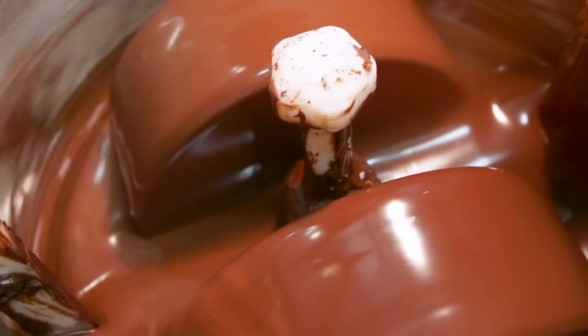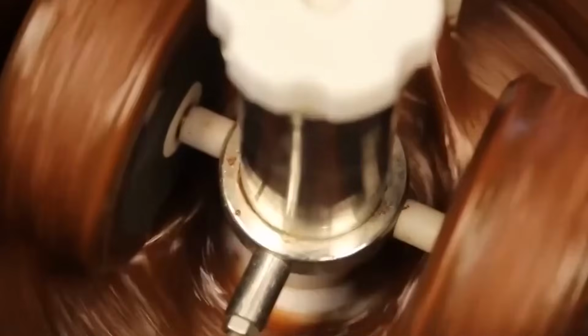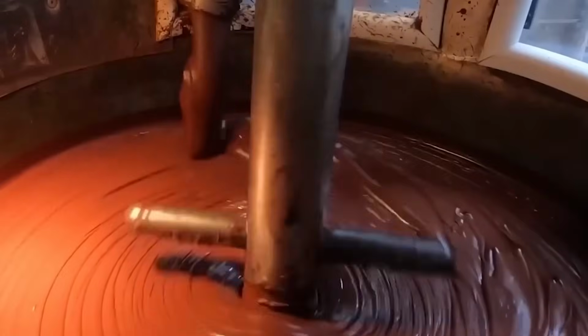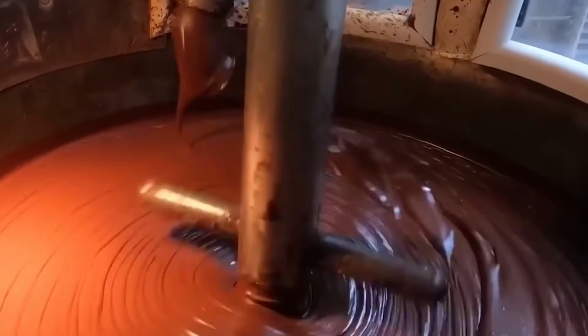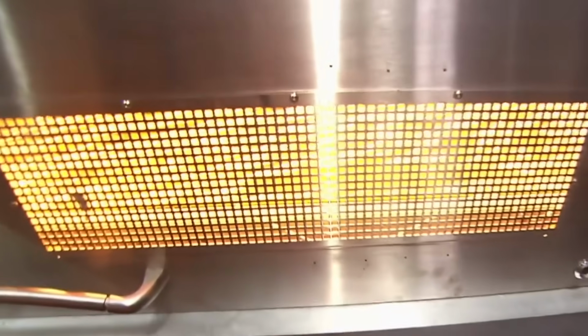Heat keeps cocoa butter fluid and allows particles to be coated. Mechanical work breaks down remaining agglomerates and distributes fat uniformly. Venting and airflow remove moisture and sharp volatiles. Moisture control is critical because even a small water content can cause thickening. Conching, therefore, holds temperature and airflow, so water leaves gradually without overheating. During early conching, the mass may be relatively dry and crumbly.